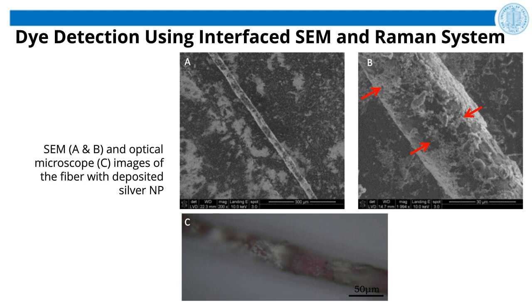In this study, we were able to measure dye stuff molecule on individual fibers. This experiment required deposition of silver nanoparticles on a single fiber segment, about 5 millimeters in size, and such analysis was not destructive, though of course it was invasive. We used two different fibers from the museum collection dyed with red-pink dye. One sample was alpaca fiber dyed with cochineal, widely used in South and Central America since ancient time. The main coloring matter for cochineal is carminic acid. Another fiber, also red in color, was dyed with Indian madder. Madder dye stuff is also a red colorant with main coloring material alizarin and purpurin.